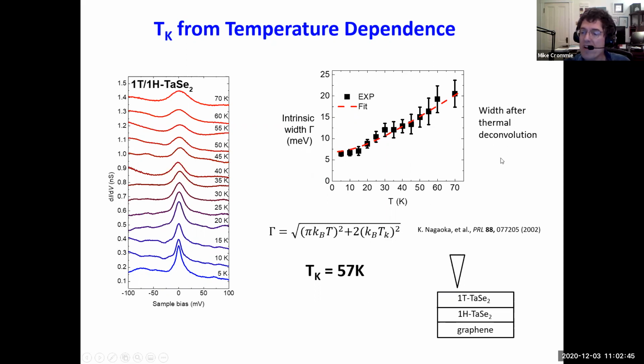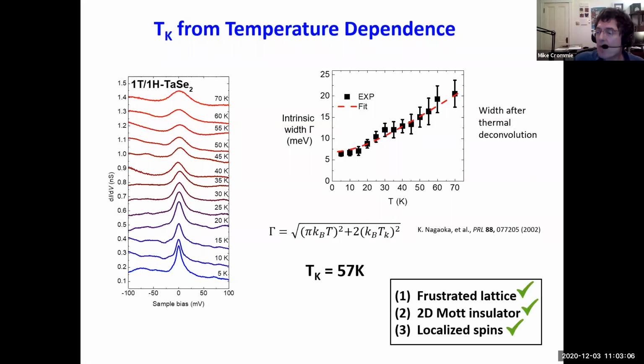And here, for the width, we have already done thermal deconvolution. If there were no Kondo effect, we would have expected just flat behavior, but instead it rose. So this is good evidence, in our opinion, that we have the Kondo effect and that we have local moments in this material. So now we see that this material satisfies all of these criteria.